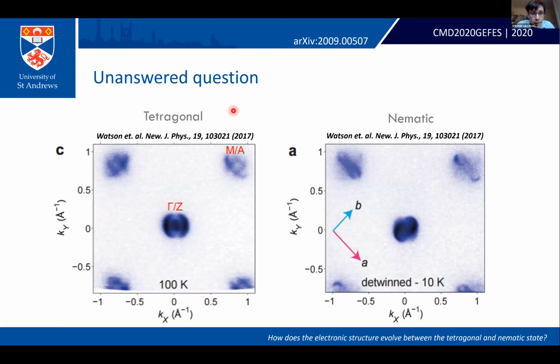In particular, how does the electronic structure evolve from the tetragonal state into the nematic state? Now, we've heard a lot about this from the experimental point of view from Amalia, but from a theoretical point of view, it's been very challenging to reproduce the experimental data that we are observing. This here is the Fermi surface as measured by ARPES in the tetragonal state at 100 Kelvin.